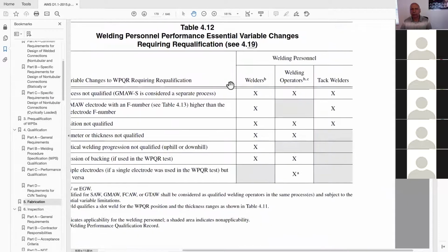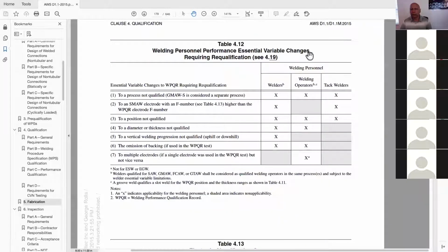table 4.12 for the essential variable changes allowed for a welder. There's nothing in there that dictates that he's only allowed to weld a particular type of steel. If he qualifies, the steel is not a restriction. If he qualifies on ASTM A36 hot roll plate, he's qualified to weld on any steel that is allowed to be welded by a D1.1 welding code. Okay, so there would be no reason to qualify a welder on a steel.